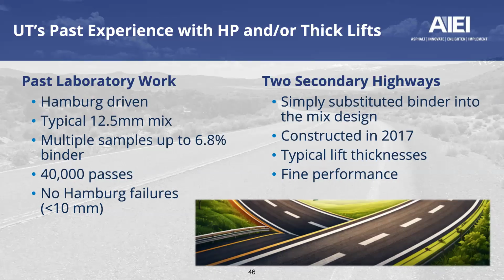They were very satisfied with what they were seeing in the laboratory from this Hamburg work. In fact, they reported no failures at 40,000 passes all the way up to the 6.8% binder content.